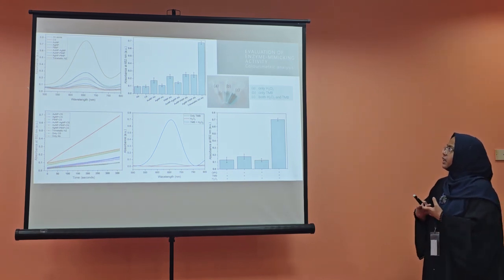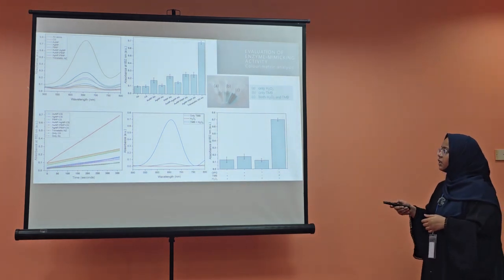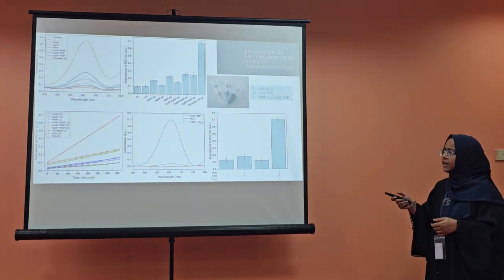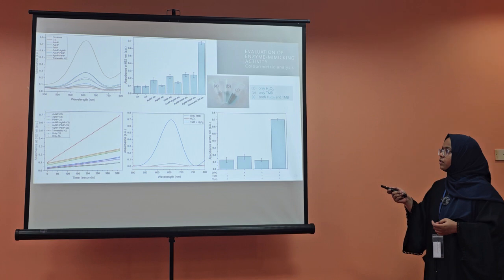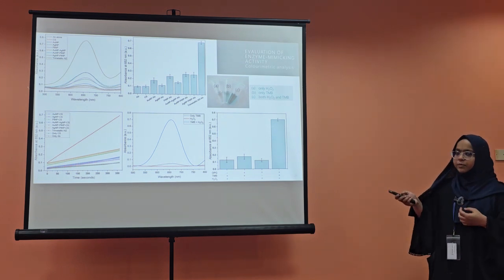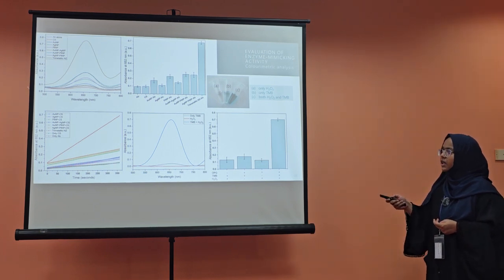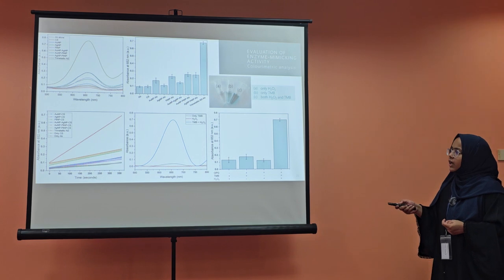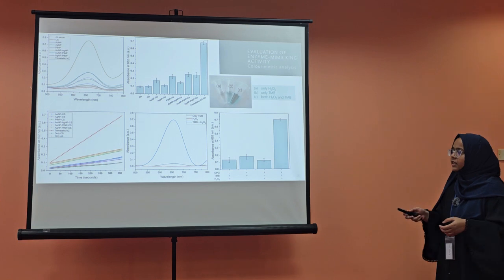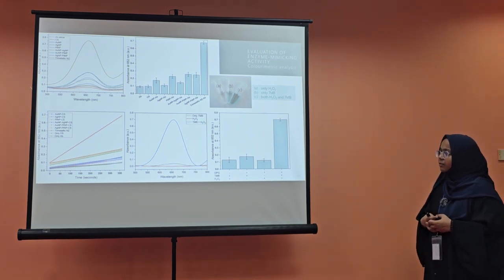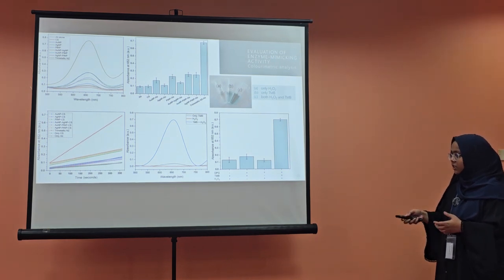Like in the previous study, the enzyme mimicking activity was assessed by checking the absorbance at 652 nanometer, and the monometallic counterparts and the bimetallic counterparts were compared with the trimetallic, and maximum absorbance was observed only when the trimetallic nanocomposite was present in the well, confirming that the maximum peroxidase activity is only when the trimetallic nanocomposite is present. Over time, as you can see in this graph, the kinetic activity of the nanoparticle increased up till 360 seconds, 6 minutes, beyond which a saturation point was reached.